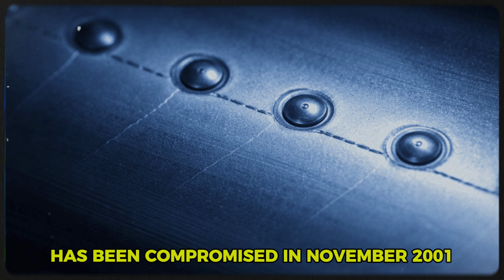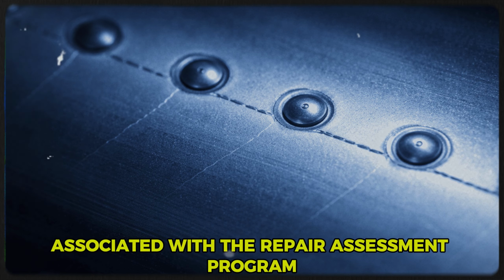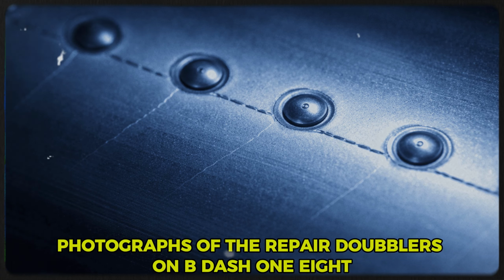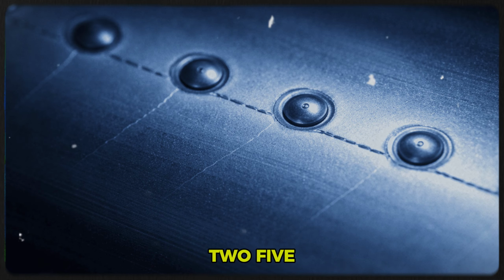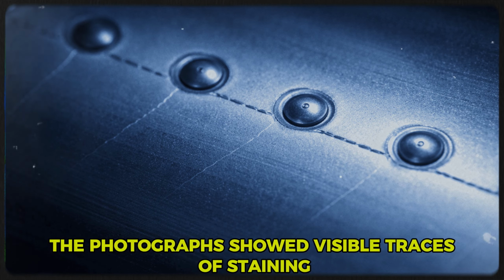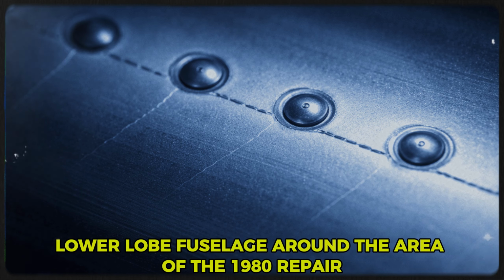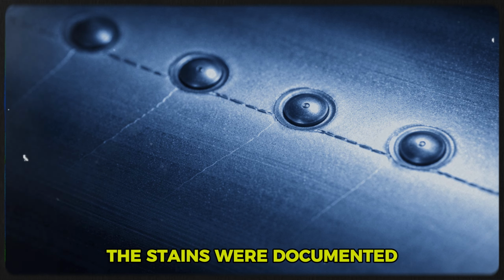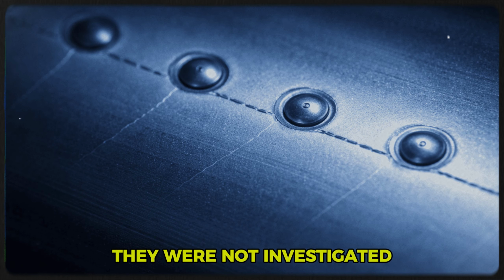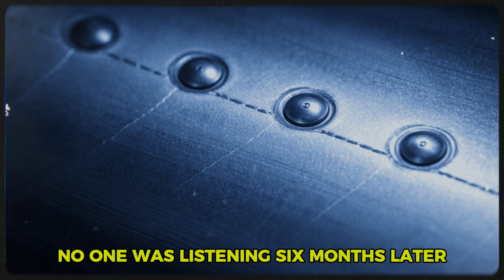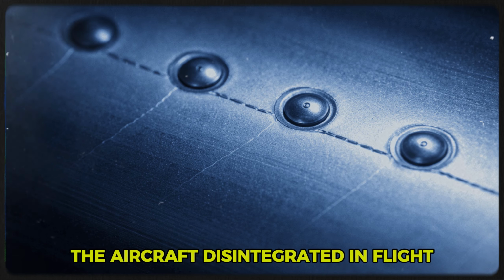In November 2001, during a maintenance inspection associated with the Repair Assessment Program, photographs of the repair doublers on B-18255 were taken. The photographs showed visible traces of staining on the aft lower lobe fuselage around the area of the 1980 repair. The stains were documented. They were not investigated. The crack had been speaking. No one was listening. 6 months later, the aircraft disintegrated in flight.